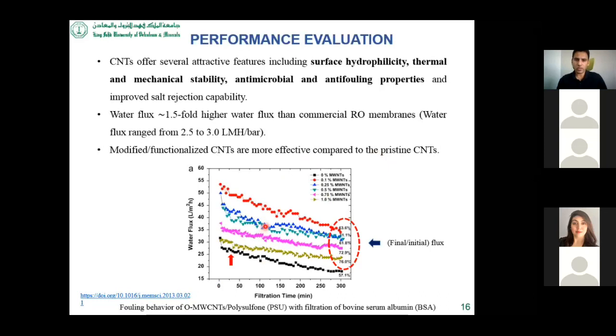So this is just one example. Here you can see that this line with the black color represents the flux through a membrane without the carbon nanotube. And you can see that water flux is very low. But if you add the carbon nanotube, here functionalized carbon nanotube is used, the flux is increased. Also, if you see the flux recovery, or the ratio of the final to initial flux, what it represents basically is, if the ratio of final to initial flux is high, this means that the membrane had less fouling, and it can be used in the long run without fouling.